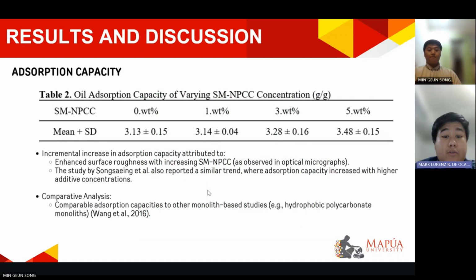Now, let's discuss the results for the absorption capacity. The data shows an incremental increase in absorption capacity with the increasing concentration of the surface-modified NPCC. This trend can be attributed to the enhanced surface roughness observed in the optical micrographs. As the SM-NPCC concentration rises, the surface area available for absorption also increases, allowing for better interaction with the oil.